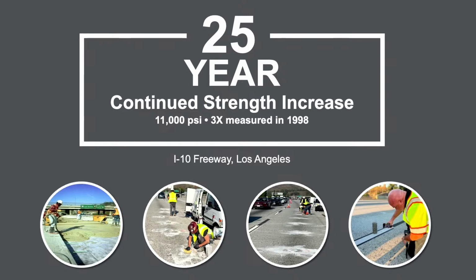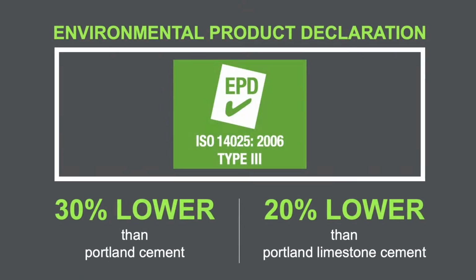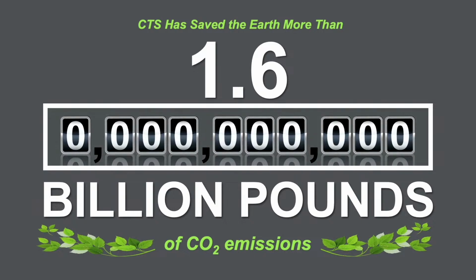And finally, the global warming potential of Rapid Set cement is about 30% lower than Portland cement and about 20% lower than Portland limestone cement. And this is because of our chemistry differences and the fact that we can burn at a lower temperature. Now, these numbers are documented in our Environmental Product Declaration, or EPD. This is a third-party certified accounting of the cement manufacturing impacts. So what this means is CTS has actually saved the Earth over 1.6 billion pounds of carbon emissions over the life of the company.